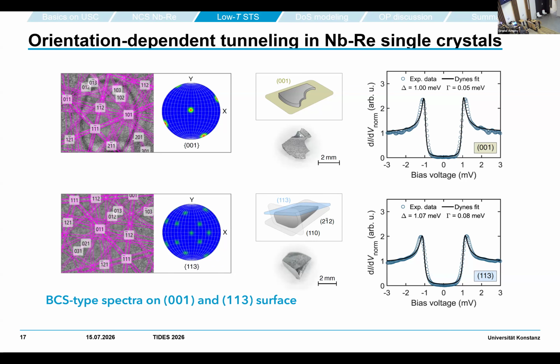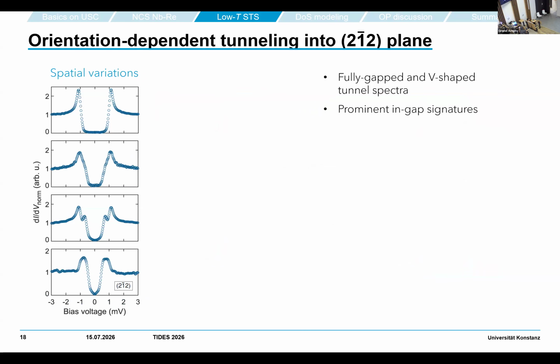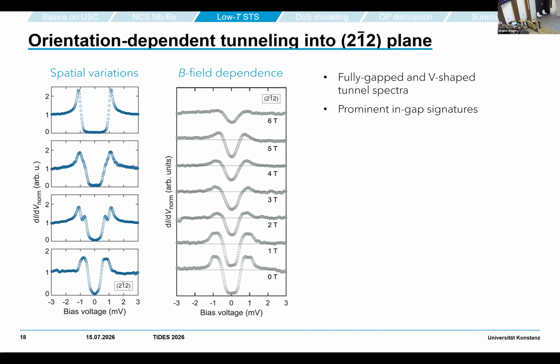Now, when we do the spectra on the 110 plane, we do again see this variation of spectra that we saw also on the thin film. So we can have fully gapped, we can have still a gap but with a kink, we can have these double peaks, and these more V-shaped in the center. We have quite some statistics that these are the typical spectra or classes of spectra that we do see.